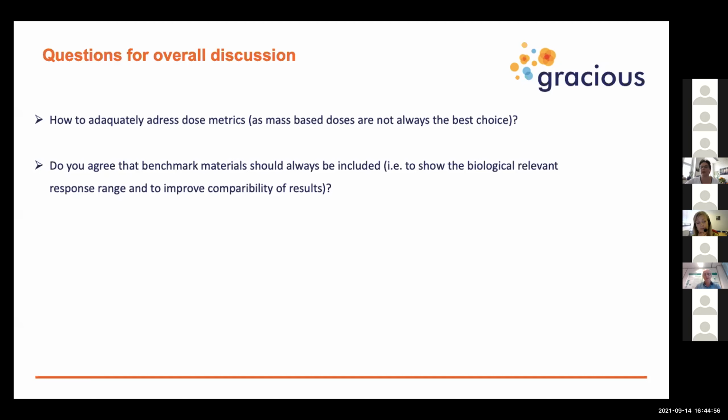And now Willy would like to speak, and then Wendell. Yeah, I apologize for slowly being able to unmute. But I basically agree with what Vicky says. What we found is that indeed surface area is a key parameter, and that is reflected in things like even the size being important in the examples that I've shown. And as I already said, it's also reflected in the fact that when you take differently shaped particles, the surface area, the volume, or any related dose metric is best describing the actual dose. So that's in line with what Vicky said, I think.